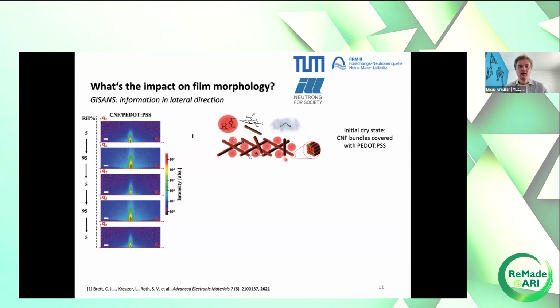This is water. We start at the initially dry state, and you see these CNF fibrils, the nanofibrils. And if you look very, very closely, maybe on the screen it works. If I give a real talk with the beamer, it's always hard to see. But these bars are reddish. So they are actually red on the surface. And this means that PEDOT:PSS has wetted these fibrils. This we measured with a complementary technique. And in between, you still have these PEDOT:PSS rich domains.